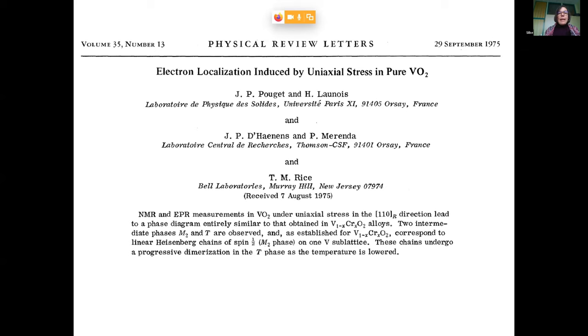And then you could again do the Peierls argument on the chain structure where you have shorter and longer bonds, but the other chain, where the vanadiums were still equidistant to each other, could be shown to be actually of Mott type in the sense that it had a magnetic response of a Heisenberg chain. That was interpreted as a signal of electron localization, which for sure was not just a Peierls transition.